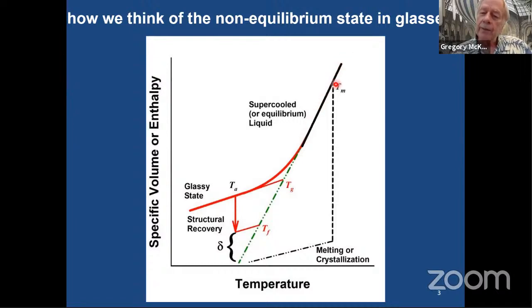sometimes we have materials that can't crystallize. So some polymers cannot crystallize. And so then we would just come down this line, or we can cool it rapidly enough that we get supercooling, like in orthoterphenyl. If I filter it a lot, I can let it sit at room temperature, which is below its melting point, for months on end, and it won't do anything. Okay, it won't crystallize, it will remain a nice liquid. So I can follow this supercooled liquid equilibrium line down.